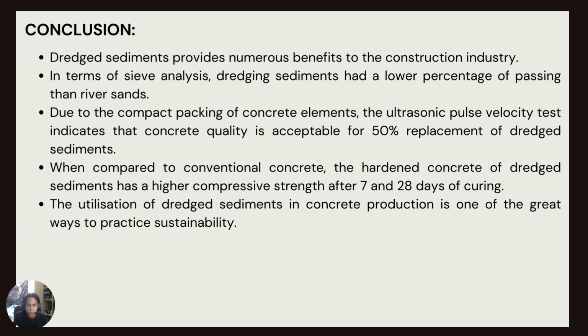So for the conclusion, the dredged sediments provide numerous benefits to the construction industry, particularly in terms of green construction development and minimizing environmental issues. In terms of sieve analysis, the dredged sediments had a lower percentage passing than river sands. This shows that the dredged sediments had more fine particles than the river sands. Due to compact packing of concrete elements, the ultrasonic pulse velocity test indicates that the concrete quality is acceptable for 50% replacement of dredged sediments. The hardened concrete of dredged sediments has a higher compressive strength for 7 and 28 days of curing when compared to the conventional concrete. Hence, the utilization of dredged sediments in concrete production is one of the great ways to practice sustainability.